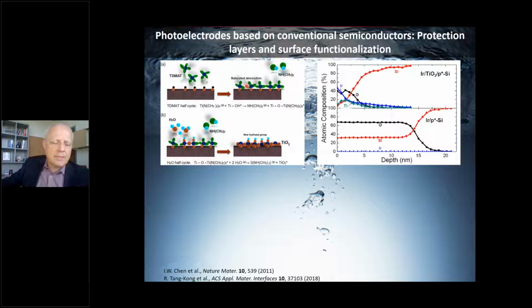And ALD is effectively a form of chemical vapor deposition in which species are deposited through a chemisorption limited mechanism. This produces a very dense packing of adsorbed molecules on the surface during the pulsing of the TDMAT precursor into the reactor. And then in a subsequent reaction step, the co-reactant, water vapor, reacts with the adsorbed precursor and produces something like a monolayer, usually somewhat less than a monolayer of TiO2. And this leaves behind a hydroxylated surface that is then an excellent surface for depositing TDMAT on top of in the next cycle. So this is a process that can be done in a sequential way, and very quickly one builds up a closed and pinhole-free thin film on the order of a few nanometers in thickness.